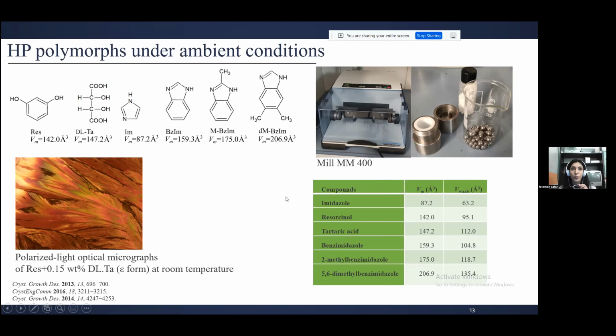Another important thing I should mention here is that the volume of the dopant, according to our idea and formula, matters. The molecular volume is really important, but the more important volume is the van der Waals volume, because it means the real size of the molecule, which, let's imagine, penetrates the unit cell. You can see here the van der Waals volume, which I calculated with software in our group that Professor Katrusiak made. It's not difficult to calculate, but with software it was much faster. You can see the van der Waals volume of tartaric acid is slightly bigger than resorcinol, but not too much.